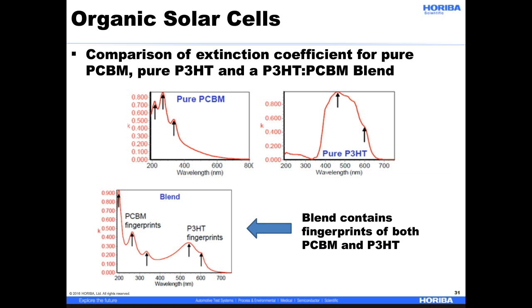I want to do a quick comparison of extinction coefficients for pure PCBM, pure P3HT, and a P3HT PCBM blend. We saw these already: the optical constants for pure PCBM along with the fingerprints, and the optical constants for pure P3HT, also showing some of the fingerprints. The blend material contains the fingerprints of both the PCBM and the P3HT.